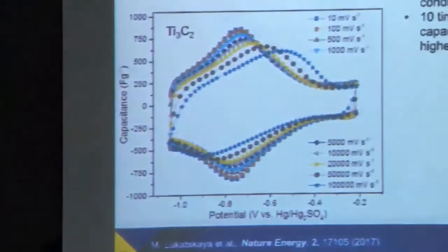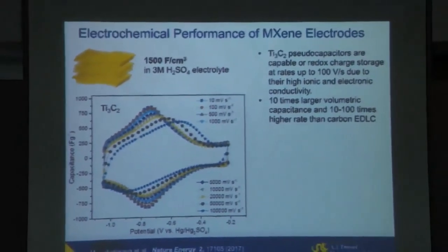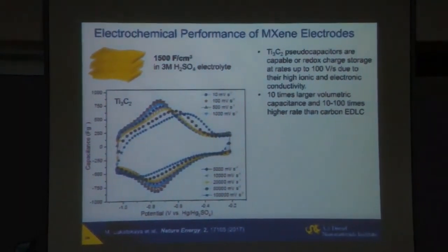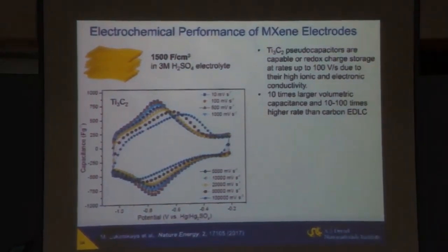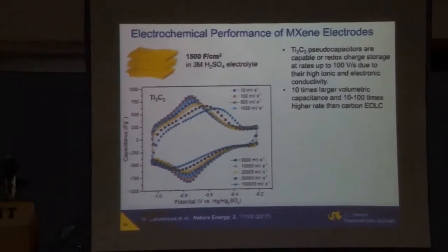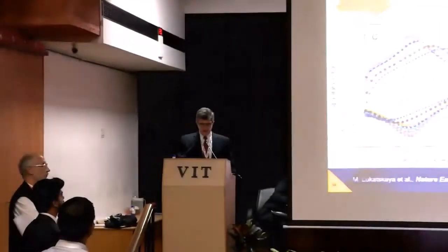Well, again, for people who are less familiar with the field, there are basically double layer capacitors, where quick charge storage is possible because of a double layer formed on this porous material surface. And there are materials which are called pseudocapacitors that charge quickly and charge is stored on the surface, but there is a redox process. So MXenes are really redox capacitors. And they show very, very high rate and enormous, actually like orders of magnitude, larger capacitance almost in sulfuric acid electrolyte. But we can get about 300 farad per cubic centimeter in organic electrolyte.